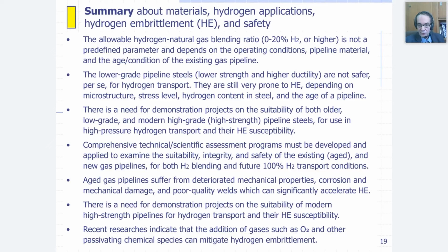Aged gas pipelines suffer from deteriorated mechanical property. I want to point out once again, the most problematic are aged gas pipelines with pre-existing corrosion and mechanical damages, with sometimes very poor quality girth welds, which represent stress concentrators, which can significantly accelerate hydrogen embrittlement and eventually failure of such pipelines. There is a need for a demonstration project on suitability of modern high-strength pipeline steels, also newly developed high-strength pipeline steels with improved hydrogen embrittlement resistance for pure hydrogen transportation.